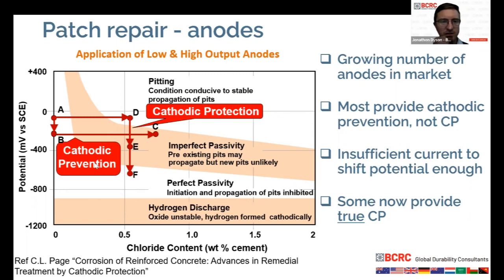Well, let's take this graph on the left here. And this is a graph of chloride content on the horizontal axis. You've got your chloride content in the concrete by weight of cement. So as that goes up, your risk of corrosion of reinforcement increases. Now, this graph on the left, you have your potential of your steel. And so if you have a normal situation without an anode, you have your potential of your steel up here, a little bit under 0 millivolts. And as the chloride ingresses into the concrete over time, you get into this pitting zone where you will start to have corrosion occurring.